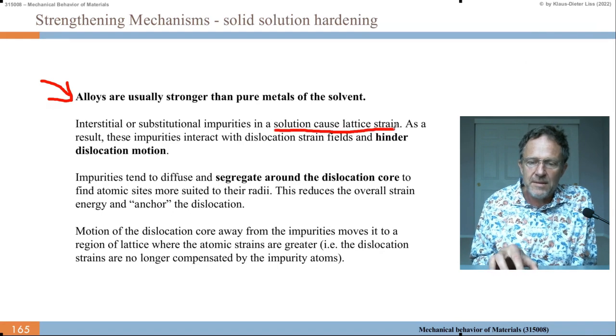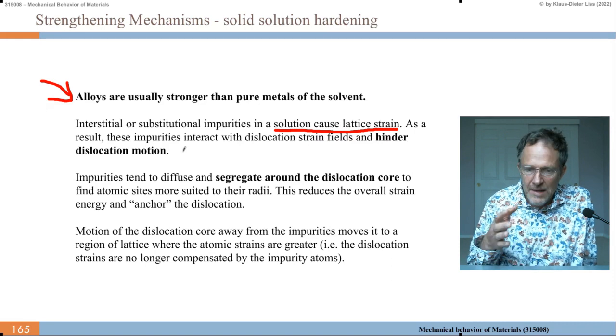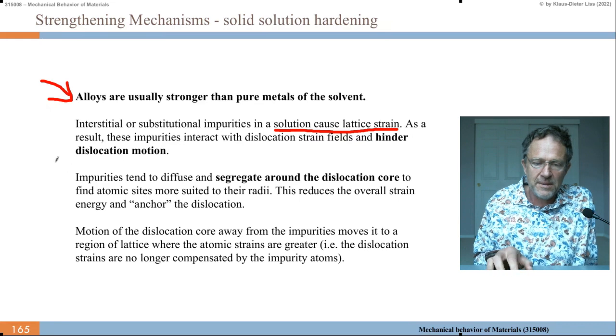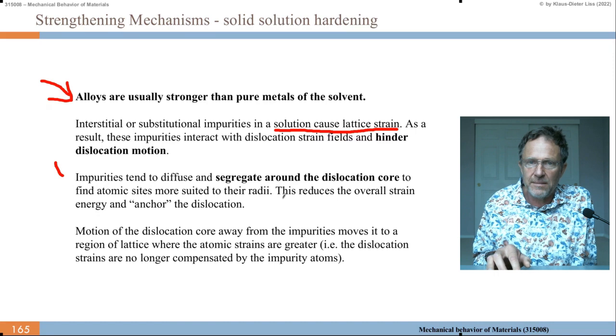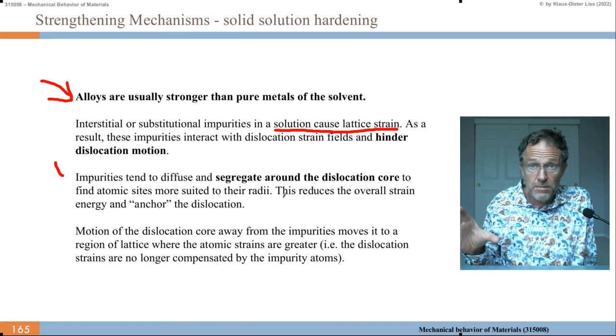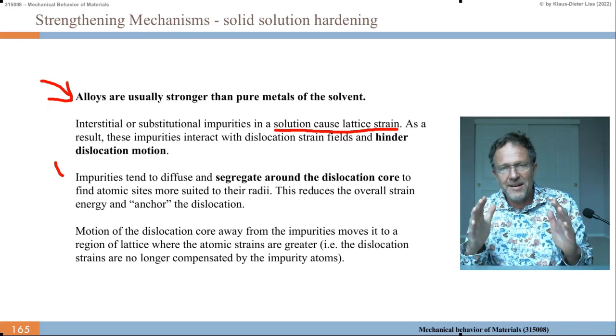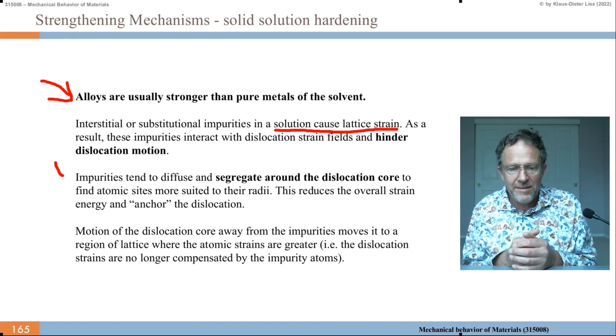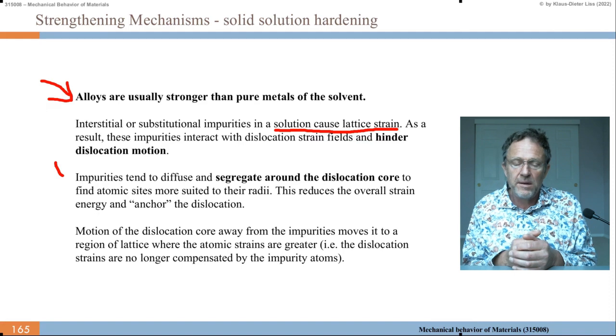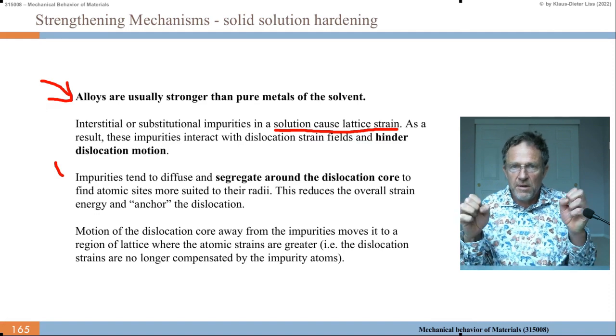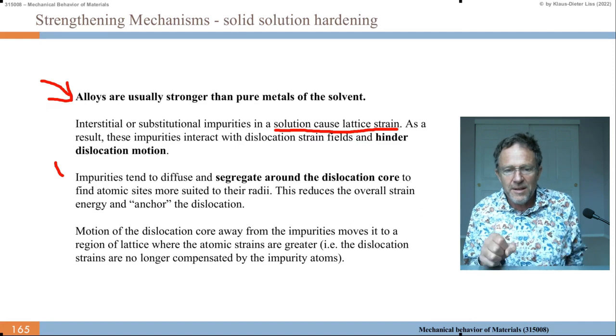So these solutes cause lattice strain. And as a result, the impurities interact with the dislocation strain fields and hinder dislocation motion, like I explained on the slide before on carbon and the Lüders band. The impurities tend to diffuse and segregate around the dislocation core to find atomic sites more suited for their radius. So the large substitutional atoms may go into the tensile, positive lattice strain areas. And if you put smaller substitutional atoms in, they may go into the compressed areas, where the lattice parameter wants to be a little smaller.